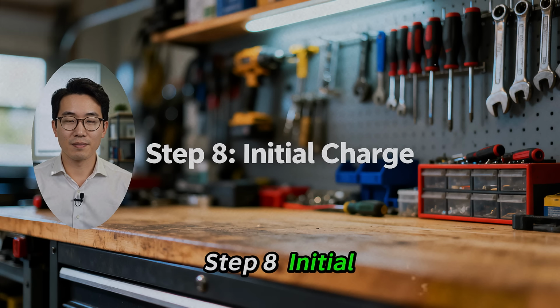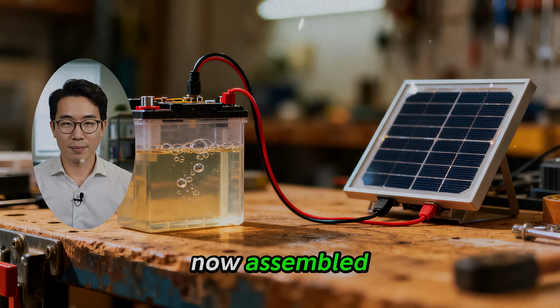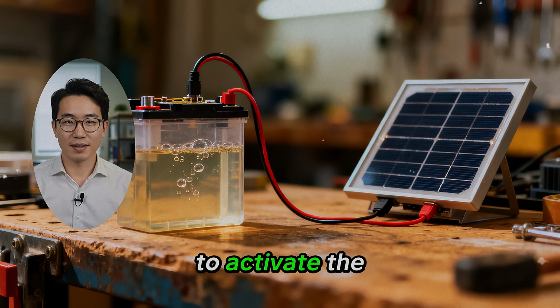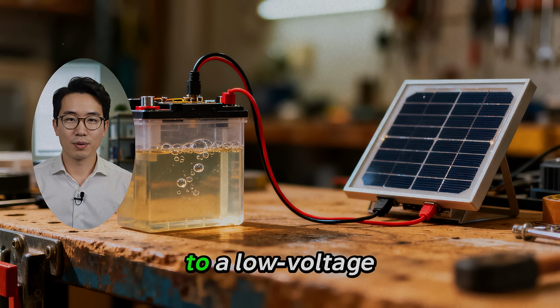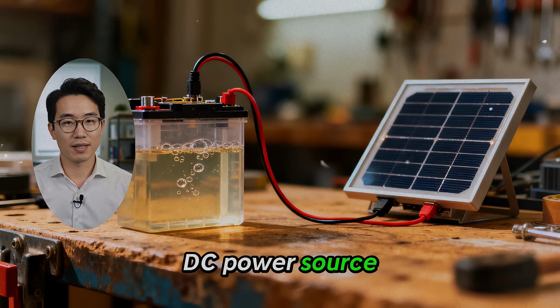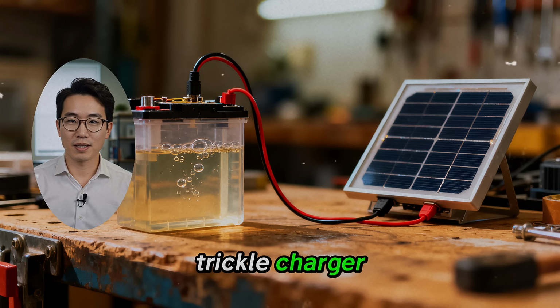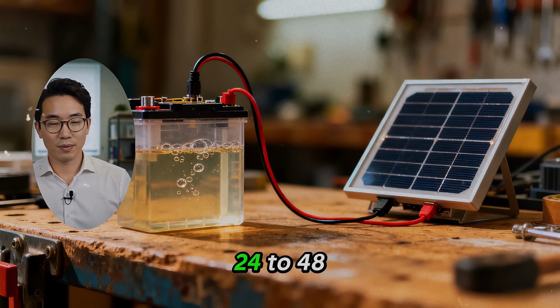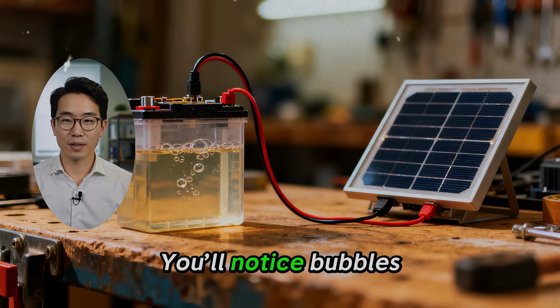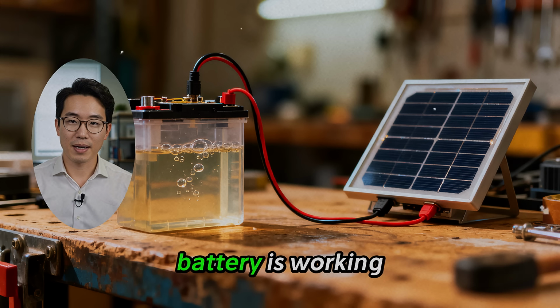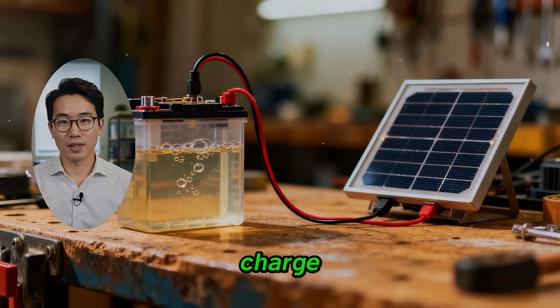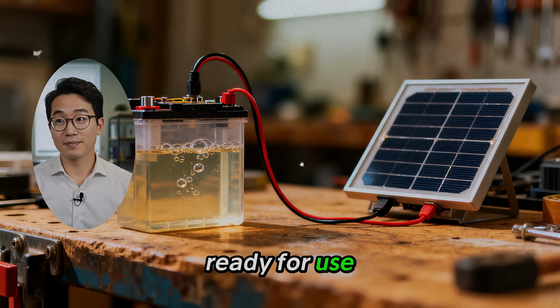Step 8. Initial charge. Your battery is now assembled, but it needs an initial charge to activate the chemistry. Connect the terminals to a low-voltage DC power source, like a solar panel or a trickle charger, and let it charge slowly for 24 to 48 hours. You'll notice bubbles forming. That's normal and shows the battery is working. After the initial charge, your battery is ready for use.